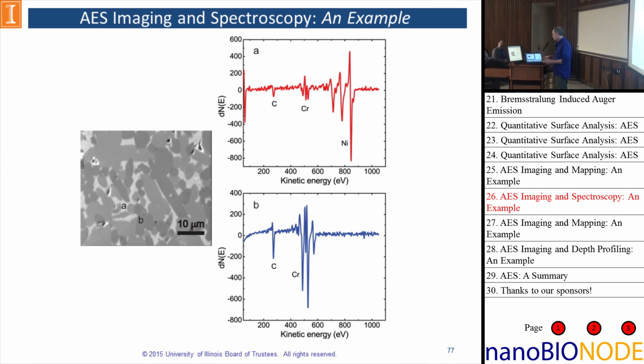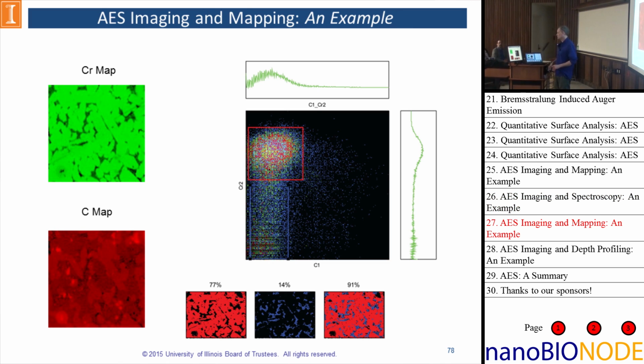And so now we can collect a chromium and carbon map. I'll use this example. We see a lot of areas that are chromium rich here, and then areas where carbon is rich are down here. And then by plotting the intensity of each of the pixels for carbon and chromium, we can look at where they correlate. And so we can now select an area here, and then an area here for the carbon, and then identify the various phases present in this material.